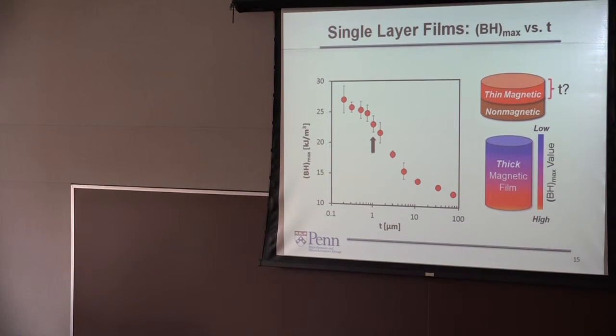So as we mentioned in the introduction, right, if you have a very thick film for a lot of permanent magnetic systems, the energy density drops as the thickness increases. And it's the same in our system, the cobalt nickel phosphorus. As you can see, there's a sharp drop between 1 to 10 micron.